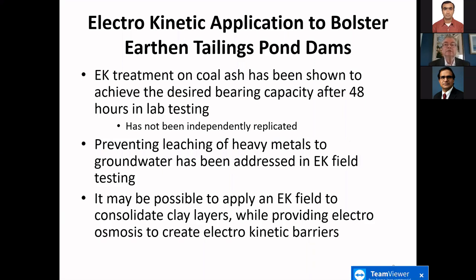So EK treatments on coal ash, we did this in the laboratory at Dr. Reddy's lab at UIC. And we saw an increase in the bearing capacity after 48 hours of lab testing. But it's not been independently really replicated, at least not to my knowledge. And as I said, it's been about 10 years since I even looked into this material.